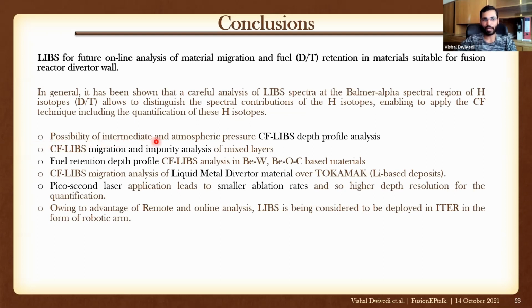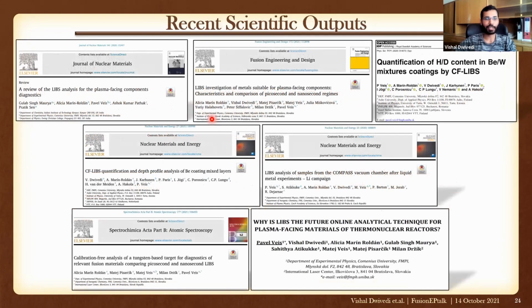So we have possibility of intermediate and atmospheric pressure, CF-LIBS depth profile analysis, CF-LIBS migration and impurity analysis of mixed layers, fuel retention depth profile, CF-LIBS analysis in beryllium tungsten, beryllium oxygen carbon based materials, CF-LIBS migration analysis of liquid material divertor material over tokamak, which was the lithium based deposits. Picosecond laser application leads to smaller ablation rates and so higher depth resolution for the quantification. Owing to the advantage of remote and online analysis, LIBS is being considered to be deployed in ITER in the form of robotic arm. These are some of the recent publications from the last 2 years from our group.